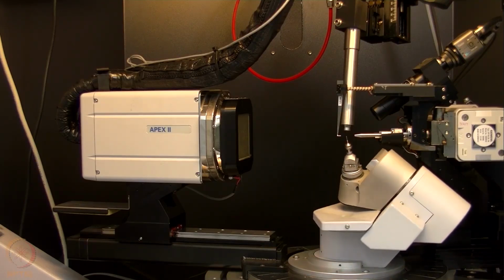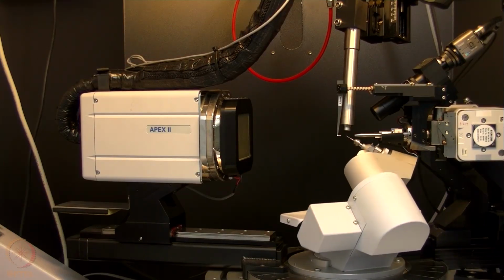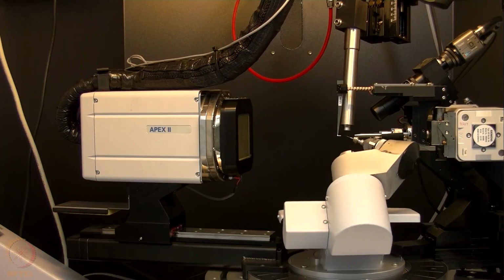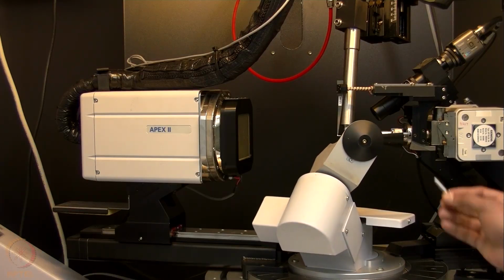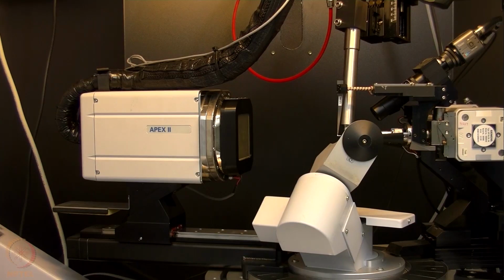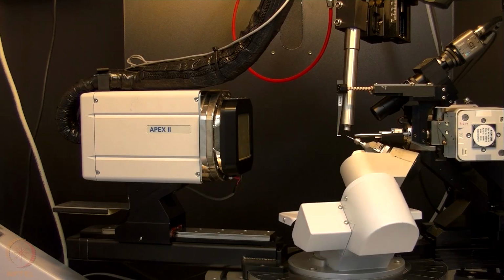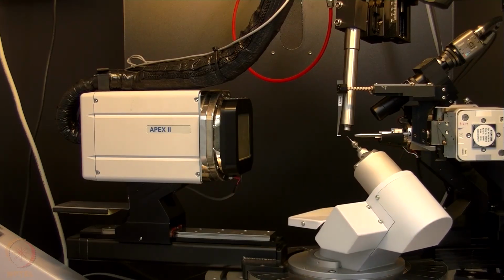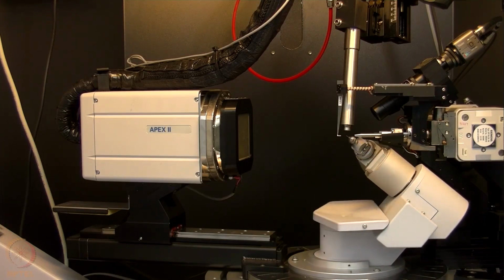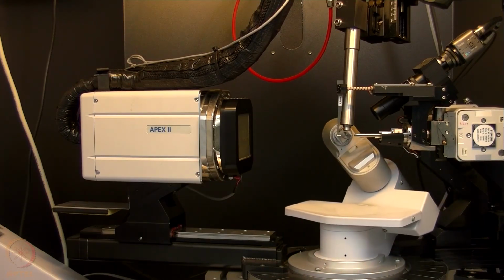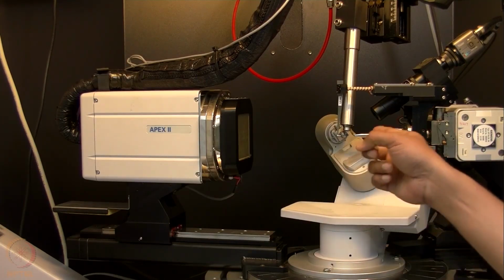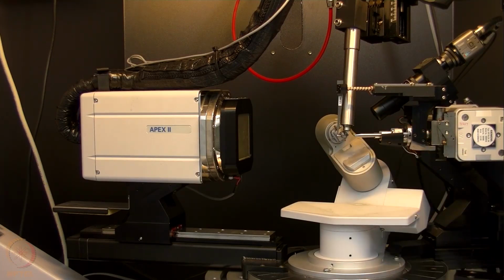See here the kappa is changing and coming to a plus 90 orientation. This is the plus 90 degree orientation of the kappa axis, which is now horizontal like that. If I go back to the right orientation, then again the goniometer readjusts and goes back to the other side with a kappa of minus 90. So now the crystal is pointing towards us and kappa is at 90 degrees with the horizontal axis. The base which is rotating here is the omega base.